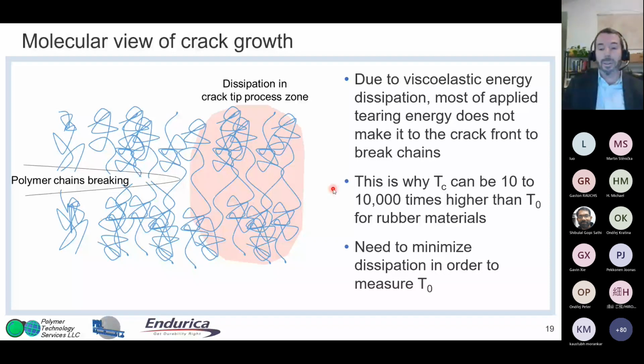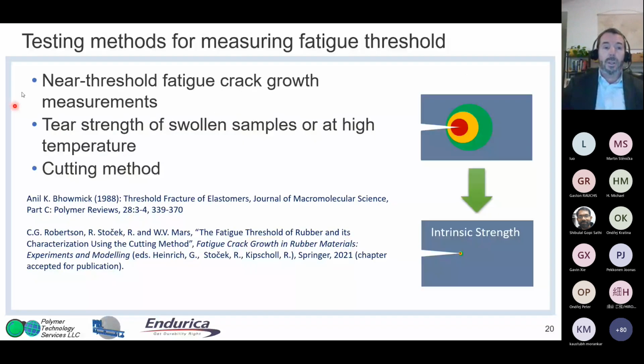Now, the problem is if you want to measure T0, you somehow have to figure out how to minimize this dissipation in front of the crack tip so you get closer to only measuring the breaking of the polymer chains. So there are three different ways of doing that. One is to measure crack growth using fatigue crack growth like I showed you, but very slow, very low tearing energy near that threshold. The second way that I'll show is to use tear strength of swollen samples or at high temperatures. Why do we do that? Well, swelling and high temperature both are a way to reduce hysteresis, dissipation. So some way to take this big crack tip dissipation zone and shrink it down so that I'm mainly measuring the breaking of polymer chains. And then the cutting method, which does that minimization and focuses the strain energy density at the crack tip using a blade.